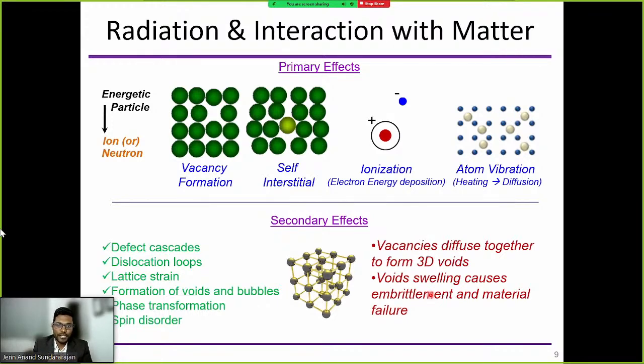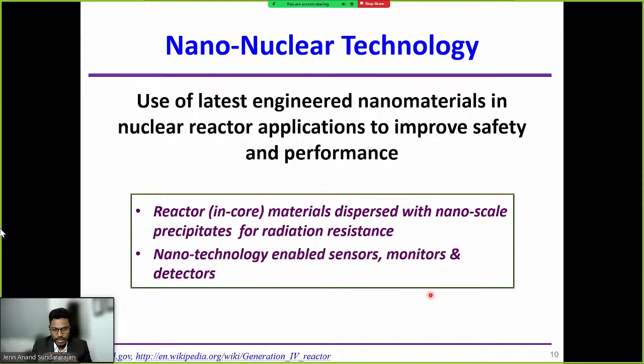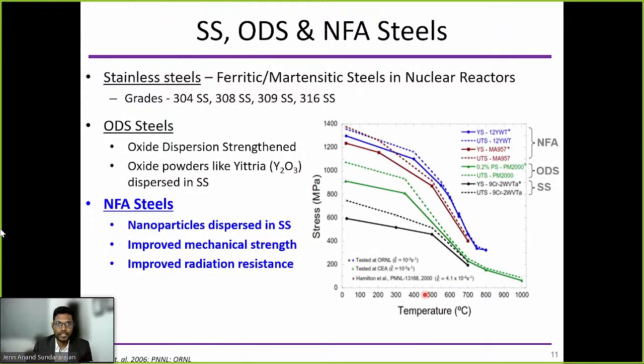This is where nanonuclear technology comes in, because we're going to use these materials to actually minimize these effects, in terms of formation of voids or vacancies. We want to minimize them as low as possible. So we are going to use nanomaterials, nanoparticles, in these stainless steel materials used in engineering. So here is a picture showing how the tensile strength of the material is improved with the dispersion of particles. If you just take a plain stainless steel, this is where the tensile stress is. But if you take the oxide dispersion strengthened steel, where yttria oxide is dispersed throughout the stainless steel, its tensile strength is even better.